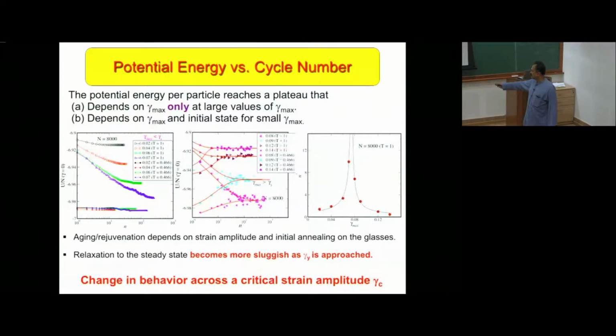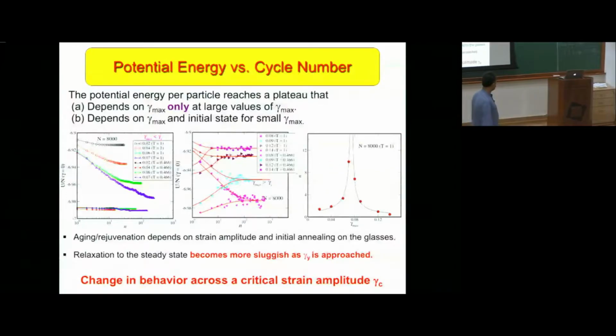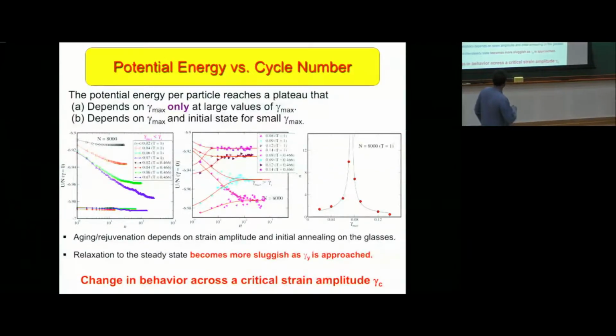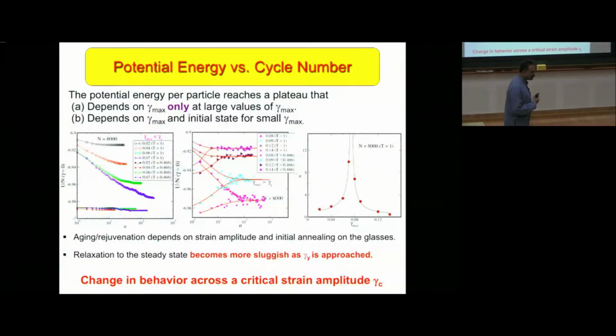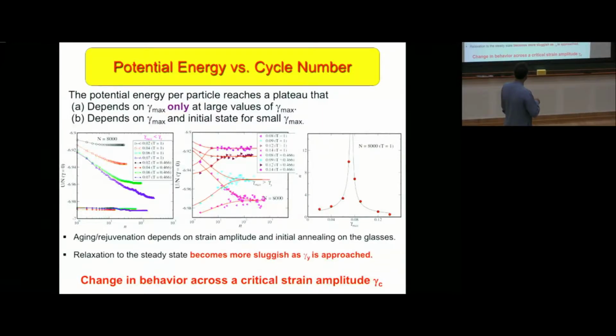You started with a poorly annealed glass, you started with a well annealed glass, you end up in the same place, right? And these energies now, as I increase the straining amplitude, are going up instead of going down, okay? So something changed between this set of amplitudes and this set of amplitudes.